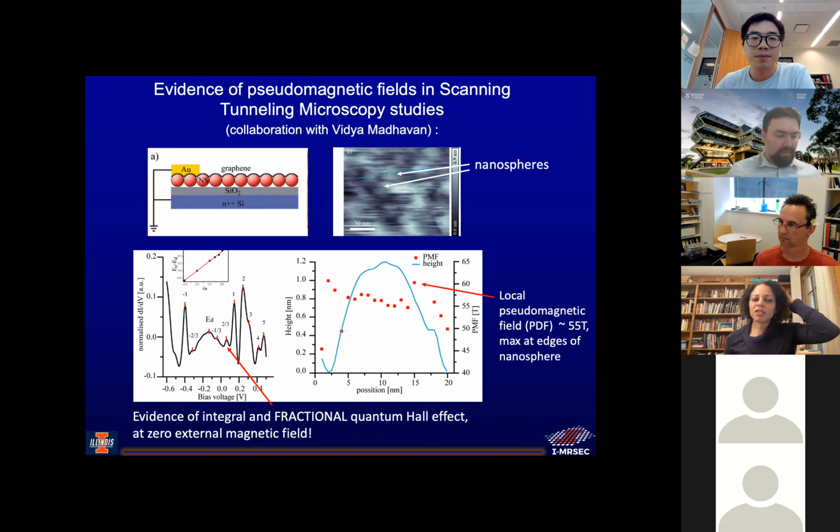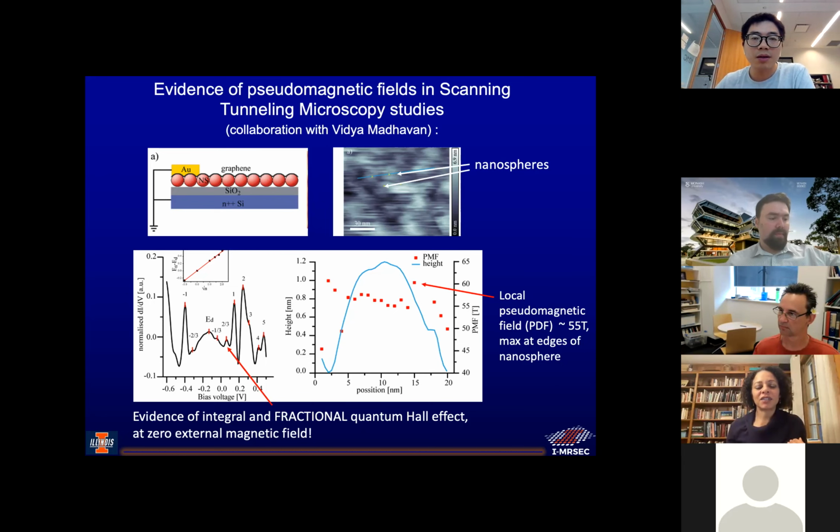So we're still trying to figure out this balance between having better crystallinity while maintaining a cleaner graphene interface, because the other thing is, if you can just get a higher quality Dirac point, you could also see all of this much more clearly. So that means maybe putting boron nitride below it or above it. But then if you put it below, then it will reduce the strain a little bit too, because that'll be strained, but not the graphene on top. So I think what you're saying is exactly what we want to do. It turns out it's not that easy with what we have right now.